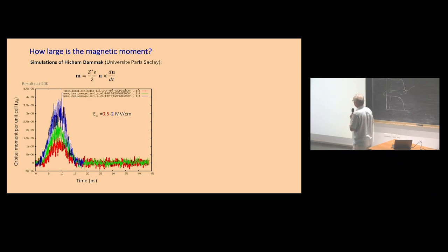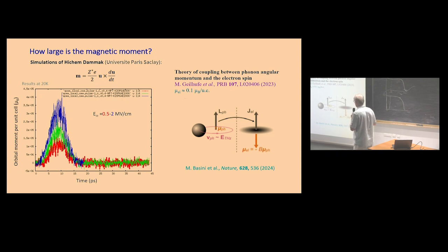The question is, how large is the magnetic moment? Theoretically, here is a calculation by Hichem Dammak from Paris. This time response should look like this. This is calculated just by taking into account the eigenvector of the soft phonon and its derivative of displacement. But note this magnetic moment should be of the order of 10 to minus 5 of the Bohr magneton. It's a very weak effect theoretically, but actually Martina showed in strontium titanate that this orbital magnetic moment is 10 to minus 1 Bohr magneton. So this is 4 orders of magnitude larger, which is a very surprising effect.